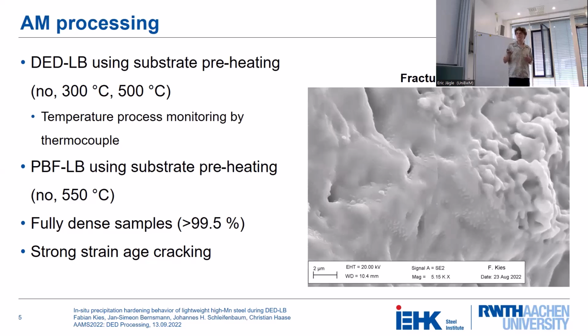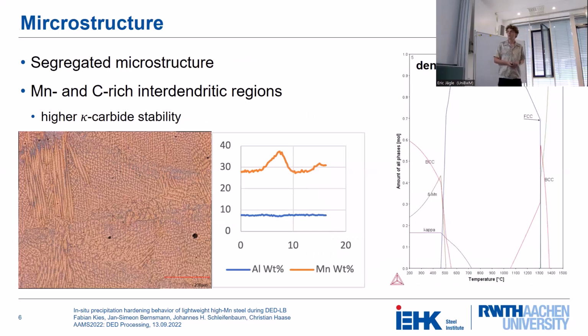But let's focus more on the in situ precipitation hardening aspect. So let's take a look at the microstructure. So here's a light optical micrograph. You can see it just looks like a DED microstructure. And if we take some EDS measurements, you can see that we have quite strong segregation of manganese in this alloy, and it also leads to carbon segregation. And this also changes the stability of the kappa carbides.